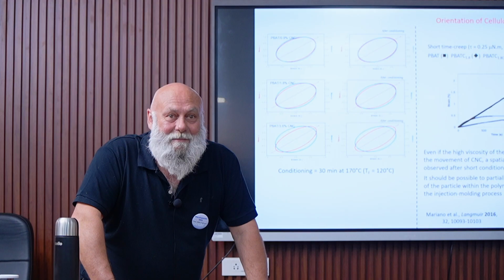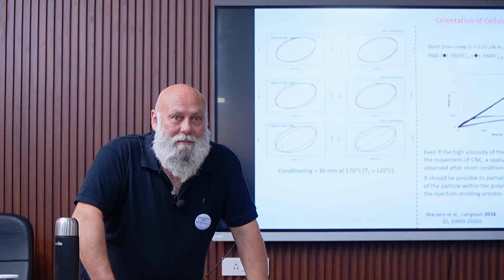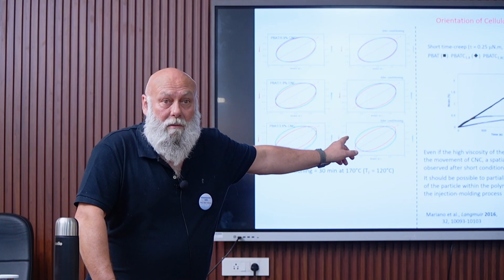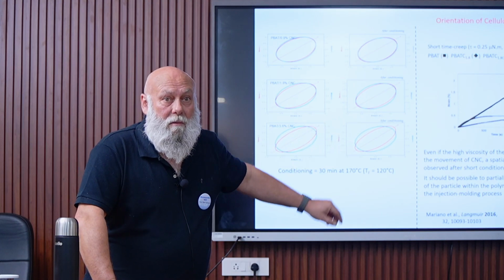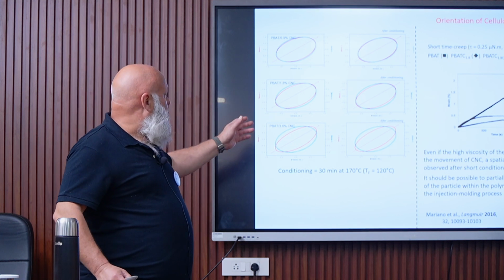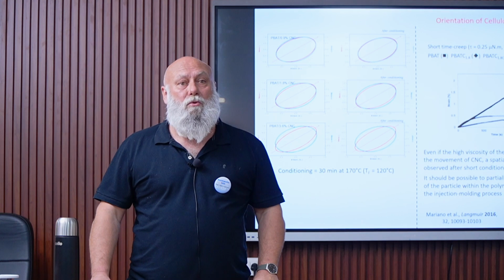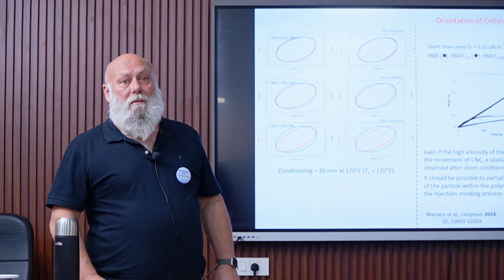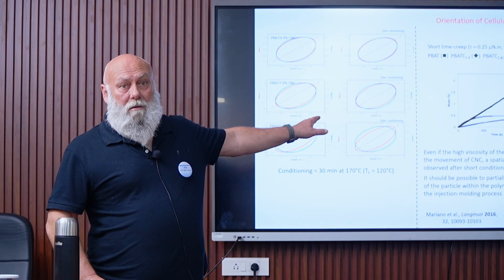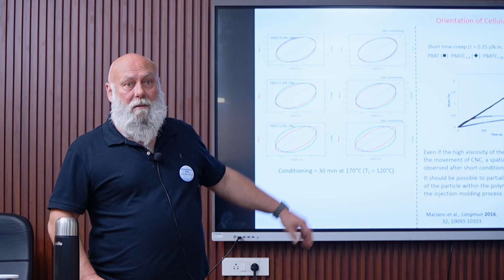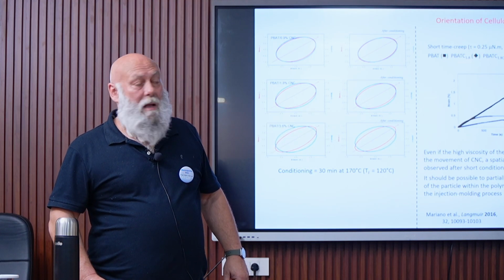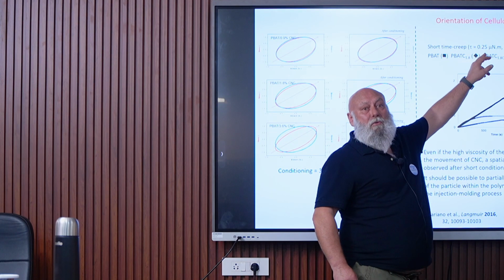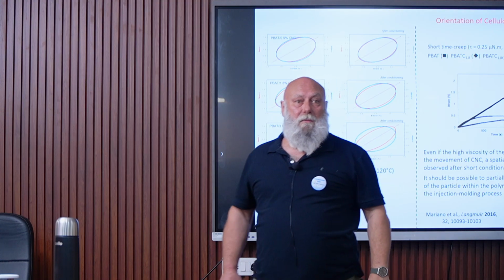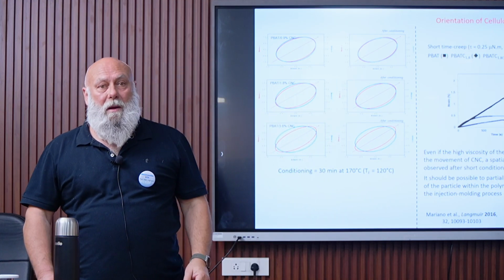It should be some percentage of the melting point, right? Here it is above the melting point. It's close to the melting point. Yes, the melting point of PBAT is around 120 degrees. And so here we are considering a polymer melt. And you can see, by the way, that the force which is applied is very low, because it's a polymer melt.